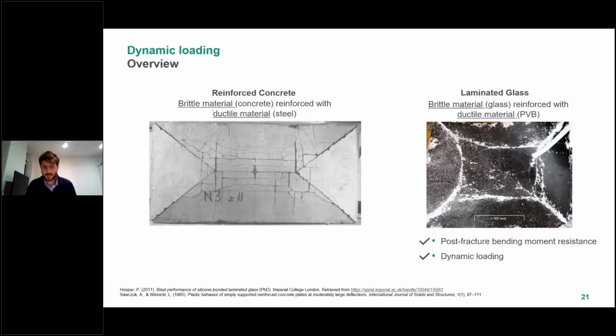Therefore, these simplified small-scale tests, namely the low-temperature bending test and the impact test by launching foam projectiles from a gas gun, were able to demonstrate that the repeated pattern that we observed from blast tests is due to an enhanced post-fracture bending moment capacity occurring due to the effects of strain rates, and due to the inertia arising from dynamic loading, we observed a different yield line pattern compared to the static loading.